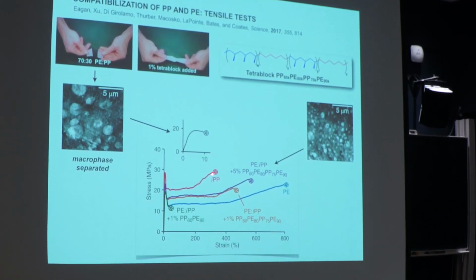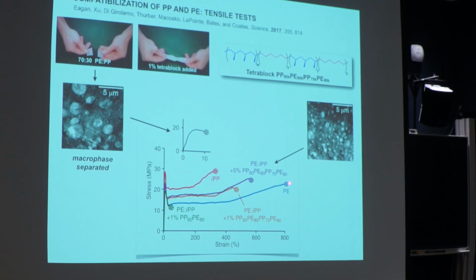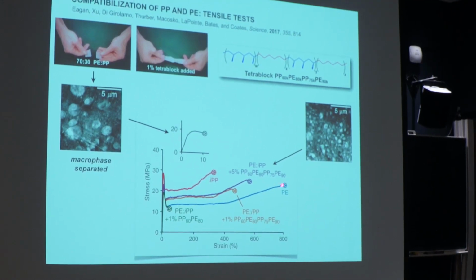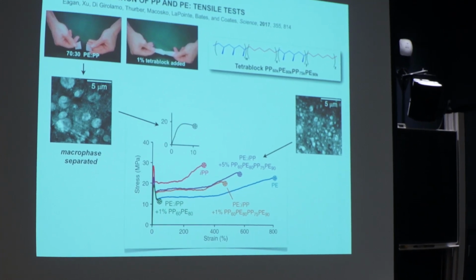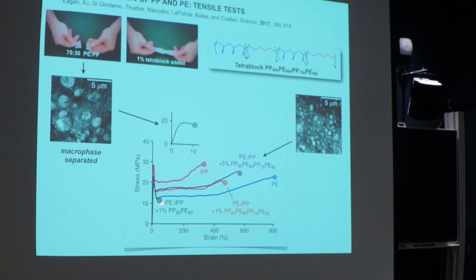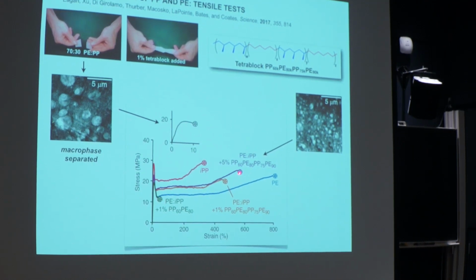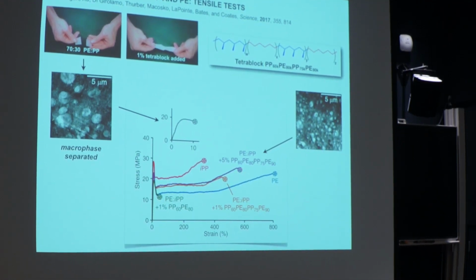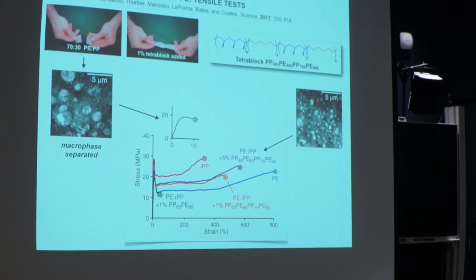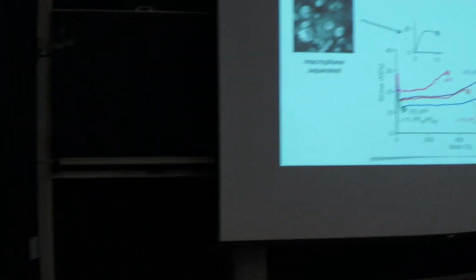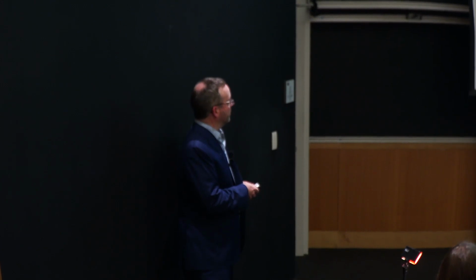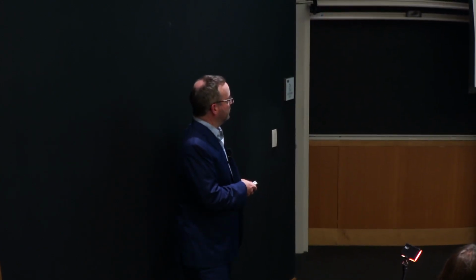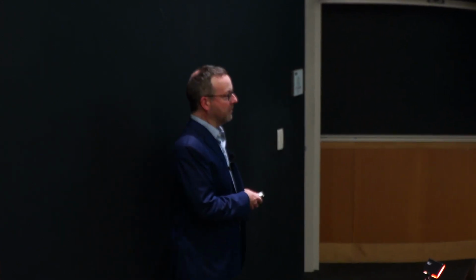Polypropylene has this stress strain plot, and polyethylene, and so you want something kind of like these materials. These are the pristine materials. When you add a diblock, it's better than adding nothing, but it's not particularly good. When you go to the tetrablock, here's 5%. These materials are interesting because they're way more rigid than polyethylene, even though they're 70% polyethylene. And you can back off to 1% and still get a material. Usually you're not taking your milk jug and stretching it 4 times its original length, right? So these have really, really good properties.